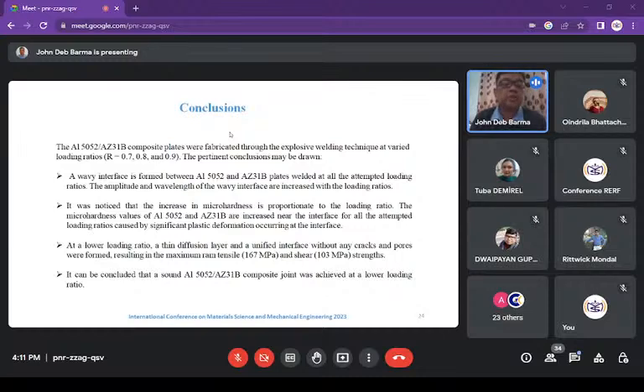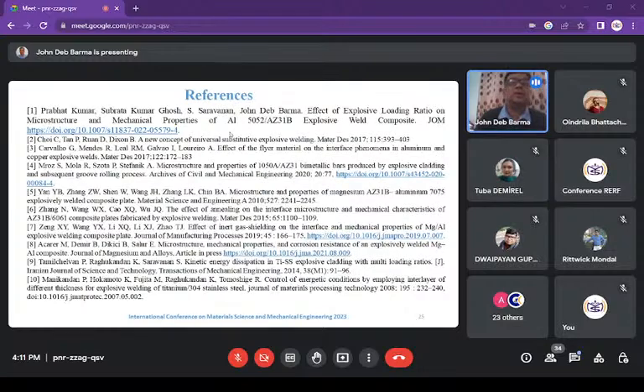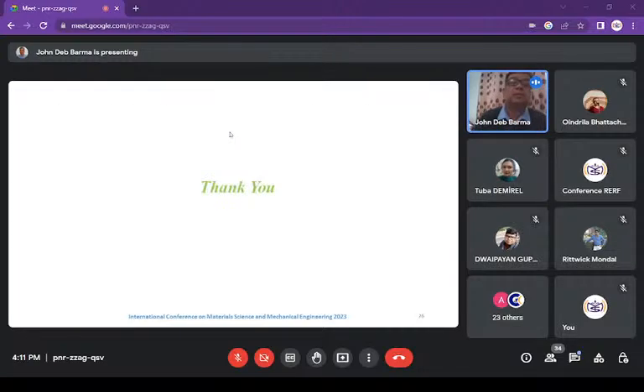At lower loading ratio, a thin diffusion layer, as well as a unified interface without any cracks, dimple formation, or pores, was formed. Since those defects were not there, it ultimately resulted in the maximum RAM tensile strength of 167 megapascal and shear strength of 103 megapascal. We can also conclude that a sound composite joint was achieved at lower loading ratios. So these are the references, and thank you.